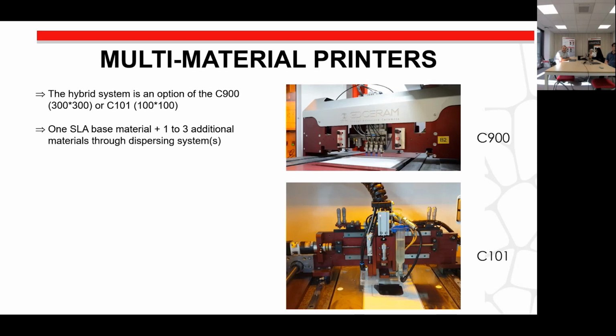So the idea is to have the SLA base material, so alumina, zirconia, aluminum nitride, whatever SLA material that you would like to use. And then you can have an additional material, 1 to 3, depending on the machine and the application, that we are dispensing through a dispensing system. So 1 material for the C101, up to 3 materials on the C900. There are several dispensing systems that are available. Micro dispensing, for example, is one of them.